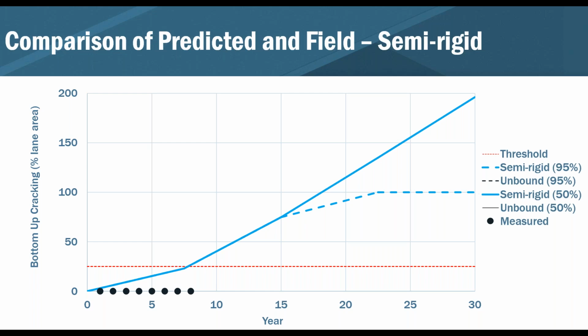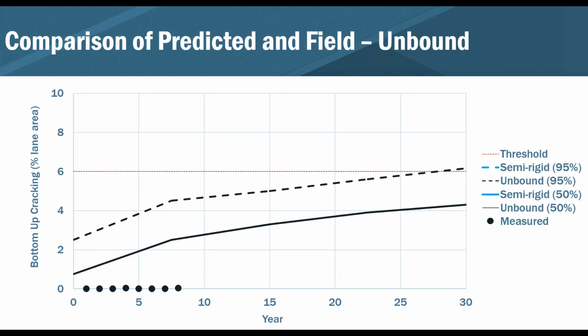So this is for the semi-rigid case. For the unbound case, it's slightly different in that the bottom-up cracking is completely related to fatigue. There is no reflection portion of this. And you can see, again, even though the bottom-up cracking is lower, it's still slightly higher, twice as high, I guess, than what is actually being measured. So again, that's something to look into, to see how come that's not tracking as well as we would hope it to be.